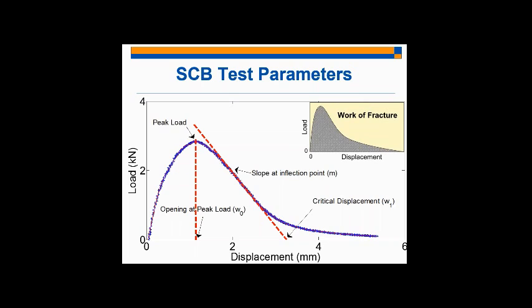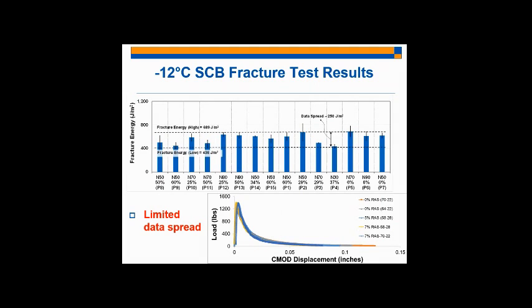And what's typically been used in the classic SCB test is simply the fracture energy. So you can see that it's just the area under the curve, and that's what's been used for screening mixtures for low temperature cracking potential. And so we went ahead and ran the test under the minus 12 degrees Celsius SCB horizontal displacement controlled condition. And the following are the results.